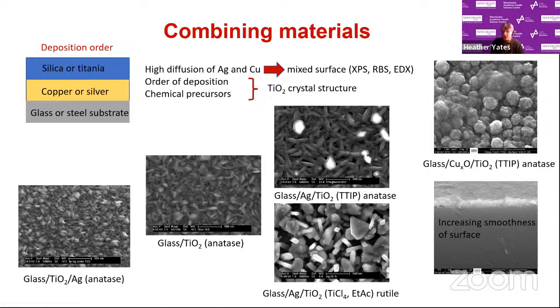On the right, I put examples of putting copper oxide down with titania. And you can see on the top, you're still getting those little island growths of copper oxide, but now they're coated with small crystallites of the titania. And gradually, as you put more titanium on, you can see that it's filling in the gaps in between and the surface gradually becomes smoother.